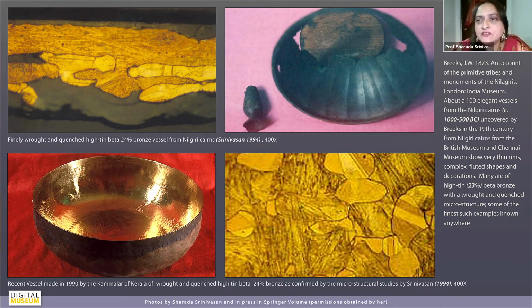And why this is significant, because bronze as such does not take so much of hot forging as such. It is because this plastic beta phase composition was being aimed for that you're able to get this. And at the same time, it has a lot of tensile strength and so on. And it has this very brilliant golden polish, which is why it was being sought. And it's also a very musical alloy. So in fact, it was also used to make a lot of musical instruments.